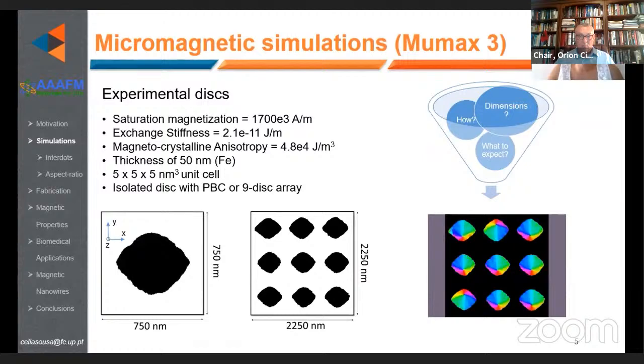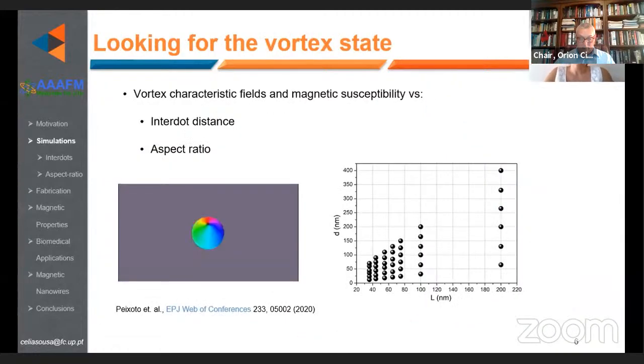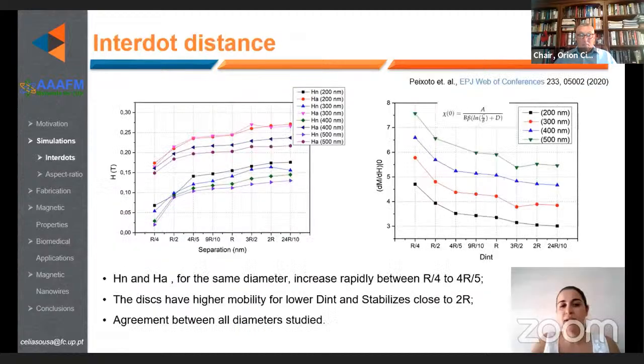Before the sample fabrication, we performed micromagnetic simulations to define the experimental conditions to obtain the nanodiscs in a vortex state. MuMax3 was used to simulate iron nanodiscs with 50 nanometers of thickness, exactly with the shape and the dimensions of the experimental samples, for both single nanodiscs and arrays of nanodiscs. Using the simulations of nanodot arrays, we studied both the influence of interdot distance and several aspect ratios, varying the values of diameter and the thickness of the iron layer in the nanodisc.